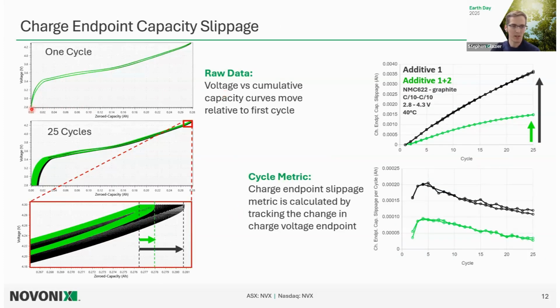So you can imagine if you charge up your cell, and if you've got all these extra electrons that you're counting, you may overshoot theoretical capacity of your cell a little bit. And then when you discharge your cell, there's a little bit of self-discharge. So you land a little short of zero on the x-axis. Then as you charge up your cell again, you're going to overshoot your last endpoint because, again, you're counting extra electrons and you started from a non-zero spot on your cumulative capacity curve. And over many, many cycles, your whole voltage curve starts to shift to higher and higher capacity.